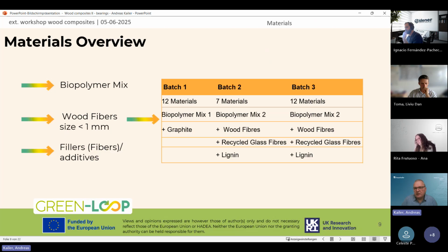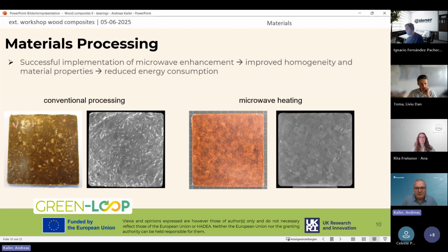We have produced in the project more than 30 different material types in different batches. Also, all of them somehow different in the mixtures of biopolymer, wood fibers, and also glass fibers, and lignin and other additives we have used. And we have produced finally very good material qualities. You can see here dense materials in normal macro photograph and CT, computer tomography images. And on the left-hand side, you can see one of the material types that is still somehow not so homogeneous.